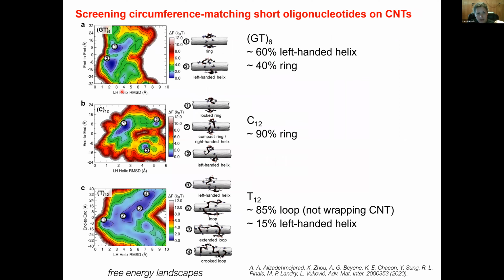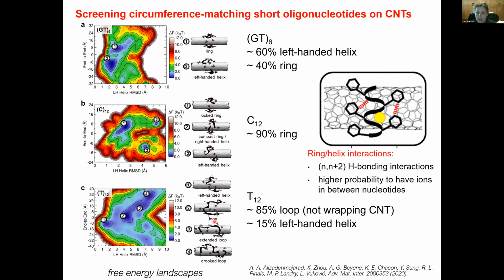We also characterized the free energies for multiple sequences. For example, GT6, we already showed that it can exist in ring and helical states. Another sequence, C12, just a 12-nucleotide C DNA, very strongly likes to form rings. That is the free energy minimum for this type of sequence. A sequence like T12, for example, doesn't like to form rings at all. It actually likes to form loops. So the conformation is highly sequence dependent. Through analysis of these sequences, we also observed what drives the ring conformations. If the bases are forming special hydrogen bonding, then that's going to lead to ring formation.